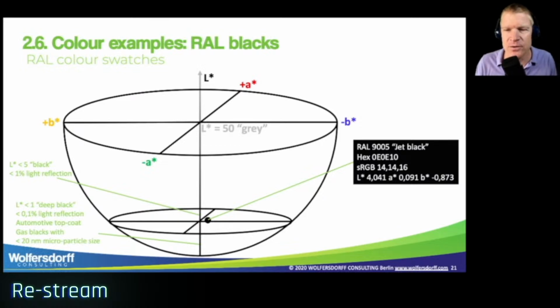But if you want to get any color into PowerPoint or Excel or Word, convert the LAB coordinates to a hex color, because you can input the hex color in PowerPoint, Excel, and Word. There's also the red, green, and blue system, but we're not using that at the moment. So you can see the L value of jet black, RAL 9005, is pretty low. It's 4, and B is really small, close to the axis, and A is also close to the axis. B is slightly negative, so we have some aspect of blueness. Generally, if we have an L star of smaller than 5, we can say this is a black color. Everything above 5 is more a dark gray color. We'll have a look at that in a moment.